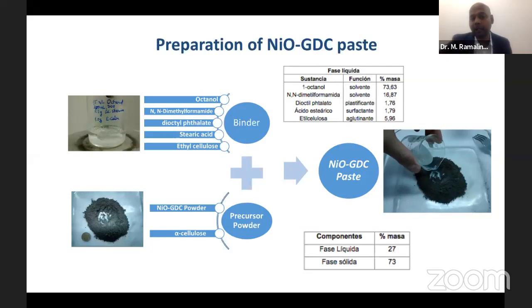Here you can find the composition, what the materials and polymers included in the paste are, which can act as a binder. Also, this can be easily extrudable, and that's more important, because everyone can prepare the paste, but fabrication without defects is more important. When we have defects, like cracks, mechanically it will not be stable.